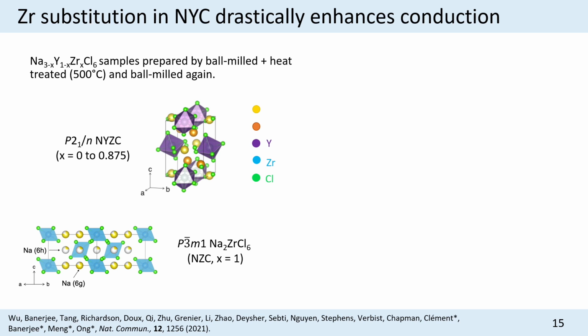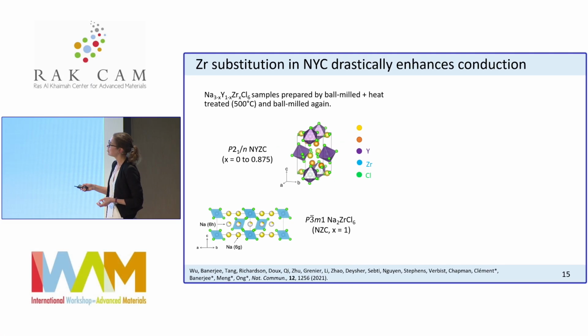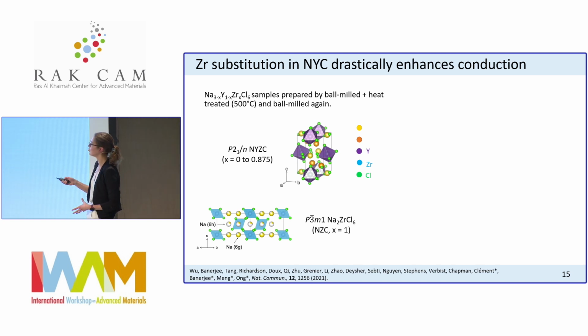And for all of the ones between 0 and 87% of zirconium substitution, we found that they all form this monoclinic structure. At least this is what we see from X-ray diffraction. So the long-range structure looks like this monoclinic material. And for the end member on the zirconium side, you form this P bar 3M1 structure, which is actually the same as the lithium version, the lithium yttrium chloride version. So now you have some vacancies, as you can see here.